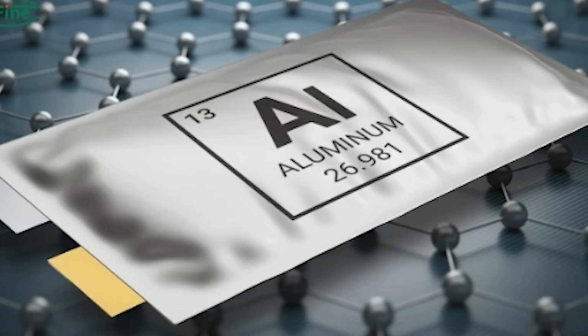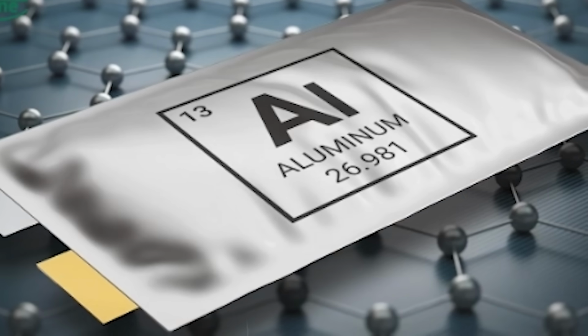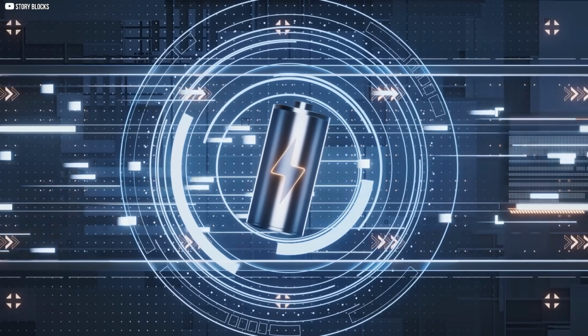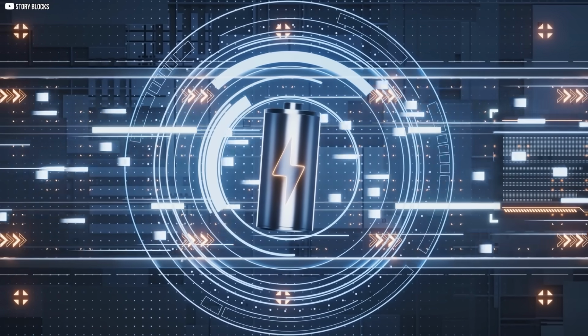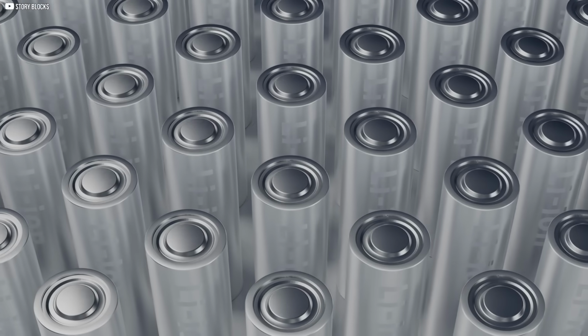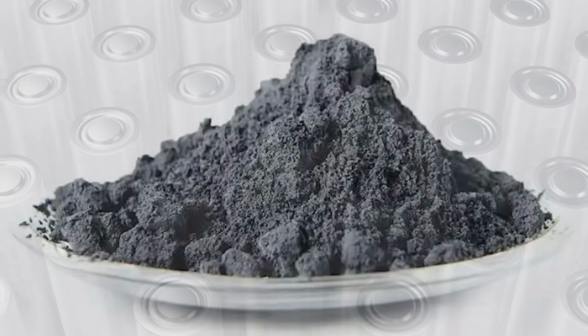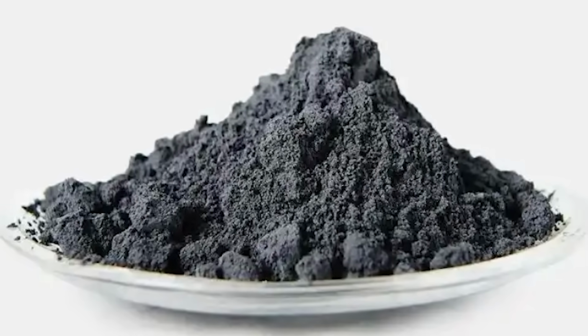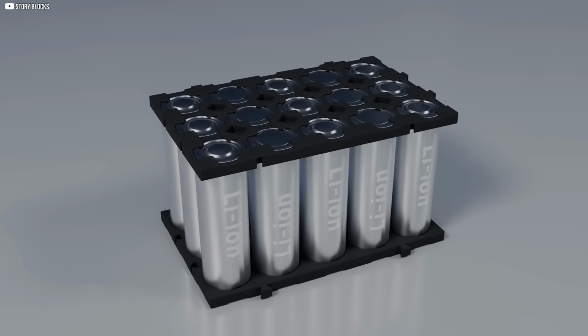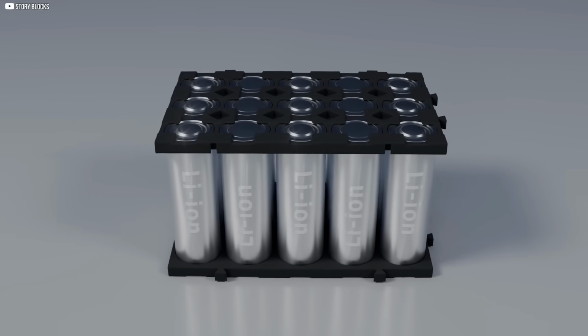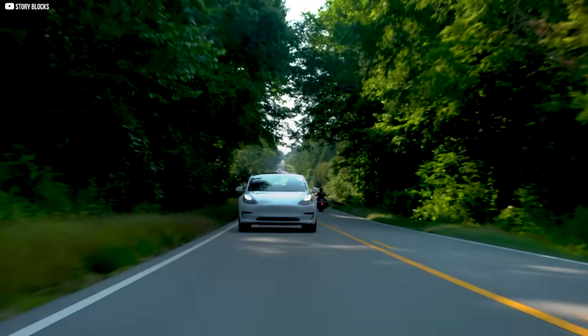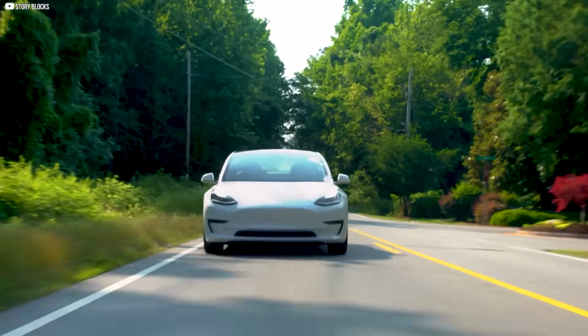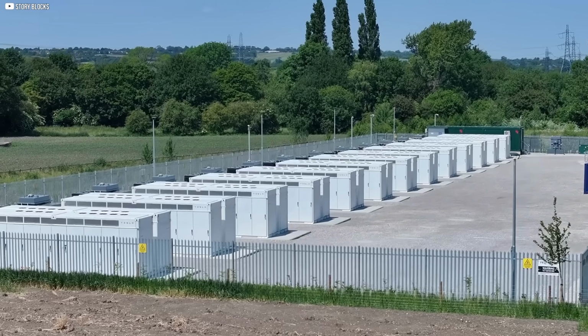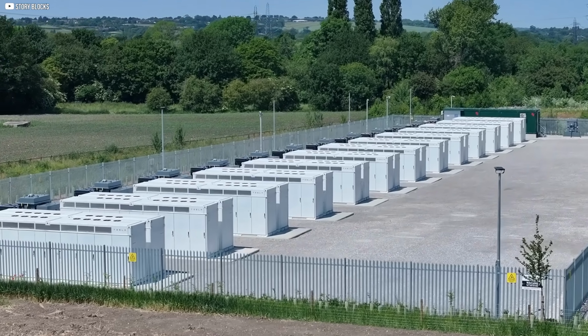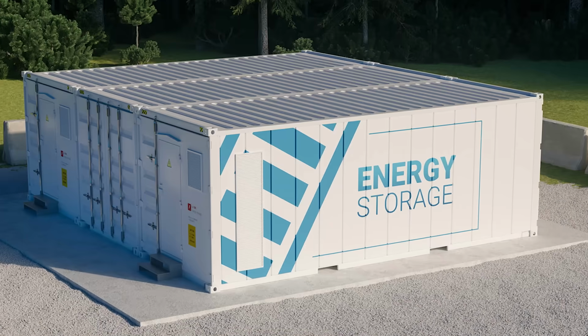Energy density, while improved, still trailed behind lithium. At roughly 150 watt-hours per kilogram, these aluminum cells offer less than half the capacity of top-tier nickel-manganese cobalt (NMC) lithium-ion batteries, which can exceed 300 Wh/kg. For electric cars chasing maximum range, that's a deal-breaker. But for stationary storage, where space and weight matter far less, the numbers are compelling.